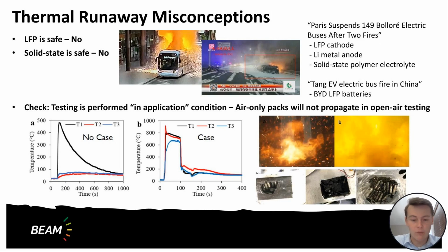21700 811 NMC cells with very minimum 2 millimeter spacing. We had no thermal management, so no PCM or other thermal management. They were just held 2 millimeters apart using PVC holders with no sort of protective materials in between. And you can see on the graph on the left that there's no propagation, and actually the neighboring cell temperatures only reached a maximum of about 80 degrees Celsius.